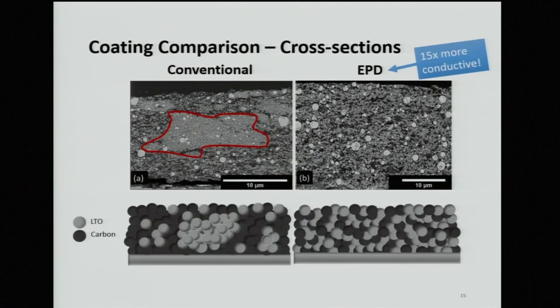Here we have the lithium titanate in gray with the carbon in black. Remember how I said that the carbon improves the conductivity of the overall material? It sort of acts as like a highway for the lithium ions and the electrons to flow through. For this material to perform, the lithium ions and the electrons have to reach the surface of the lithium titanate to react. And when lithium titanate is in contact with carbon, this happens very fast. But what about this middle lithium titanate?